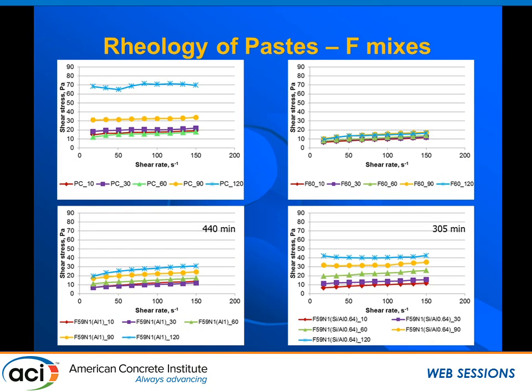For the nanoboehmite, something seems to be happening at 120, but not significant. And then for the silica-alumina ratio of 0.64, definitely something is going on. Not only is it increasing, but the slope at 120 minutes is inverted.